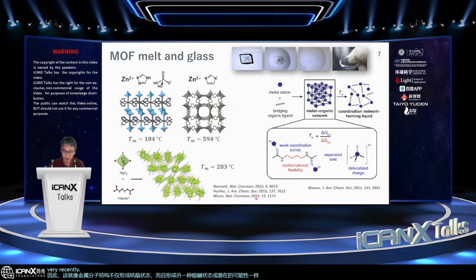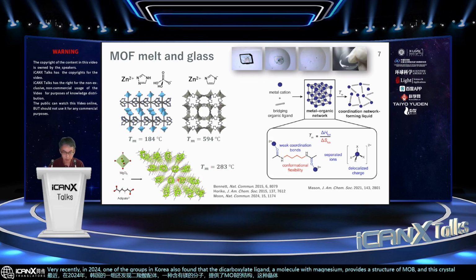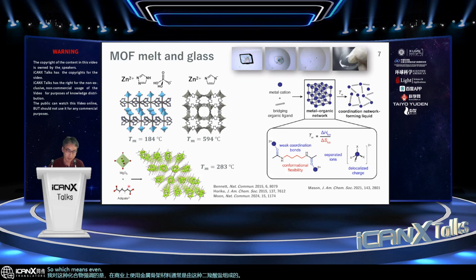Very recently, in 2024, one group in Korea also found that a dicarboxylate ligand with magnesium provides a MOF structure, and this crystal melts below 300 degrees C. I highlight this compound because commercially used metal organic framework materials are usually composed of dicarboxylates. This means that even by using dicarboxylates and commercially available MOFs, we can potentially get not only crystalline but also glassy states.